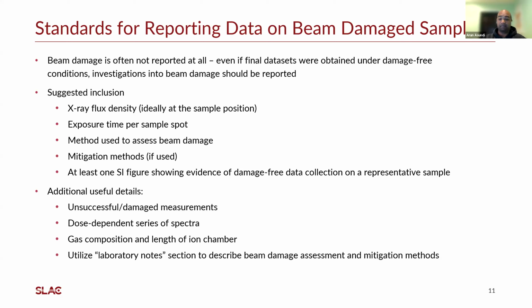But some of the mechanisms, like if particles are agglomerating, or if a species is dissolving into solvent and moving out of the beam, that may be visible by, for instance, the edge step, which could increase or decrease. So there's a few features that you may need to keep an eye on. Not just the spectrum itself, but also things like the edge step.